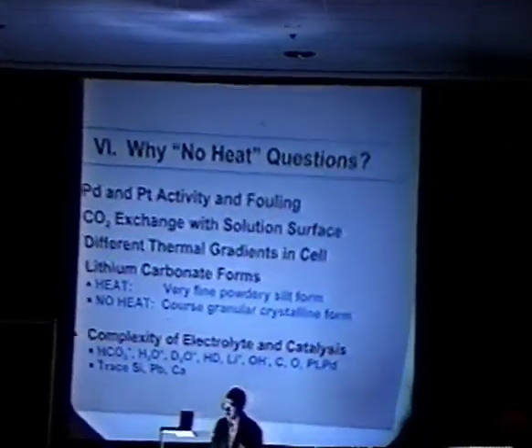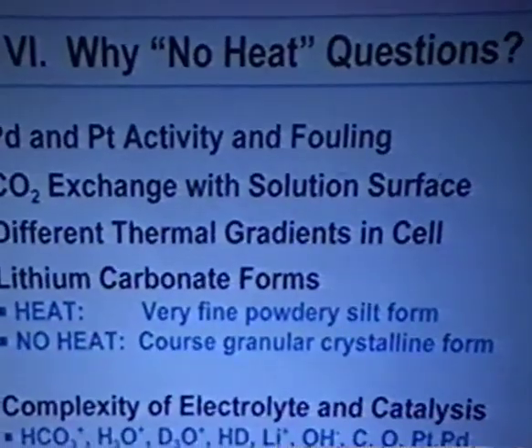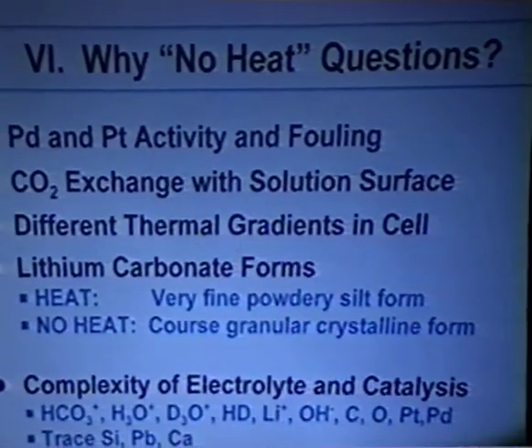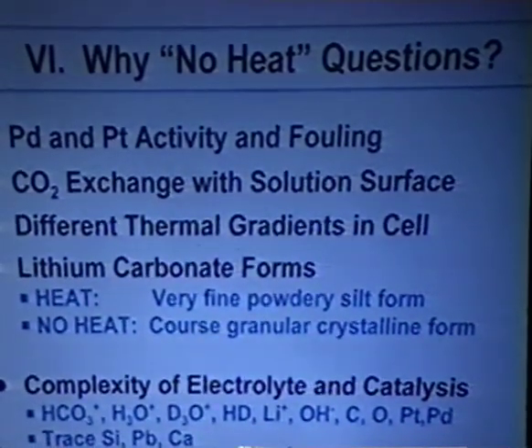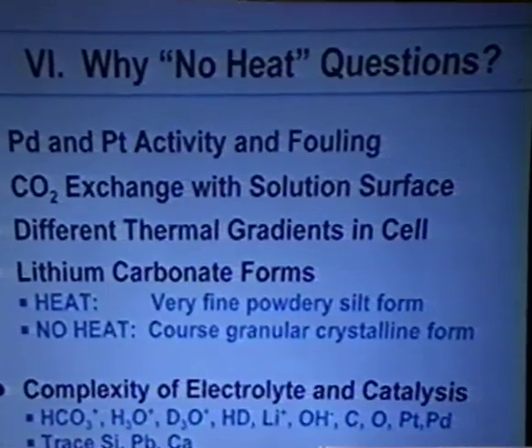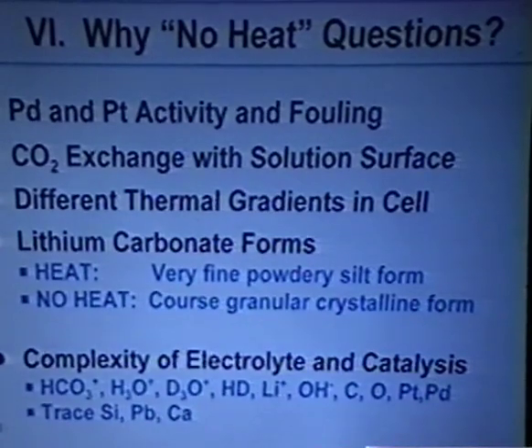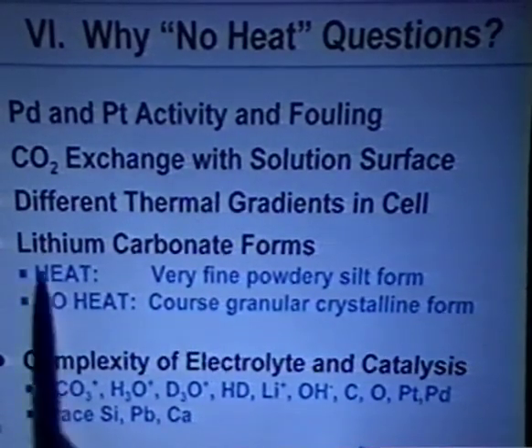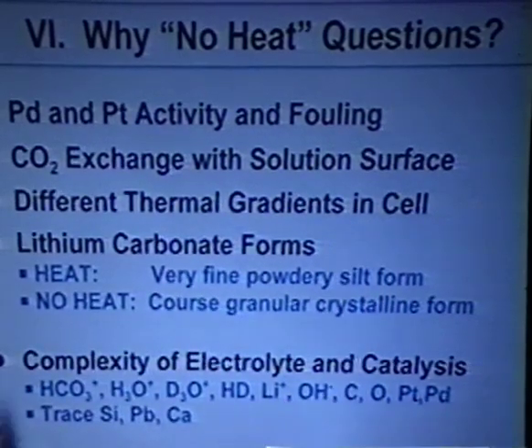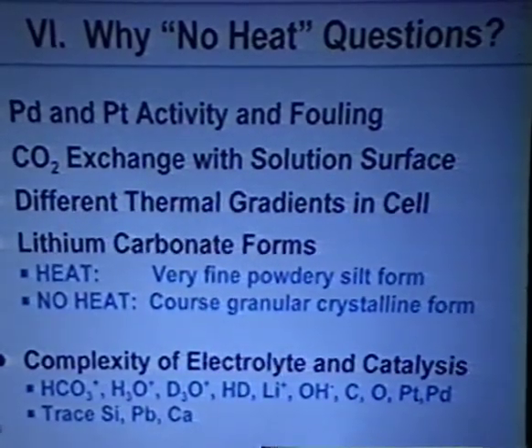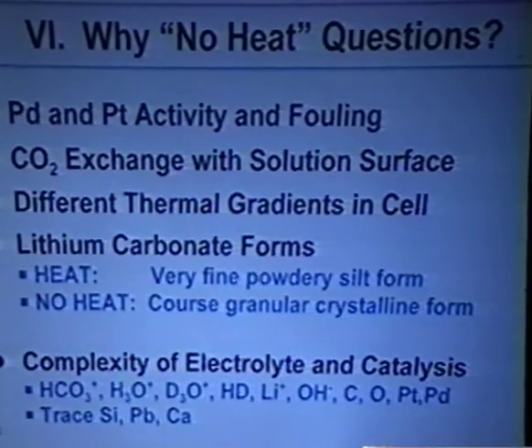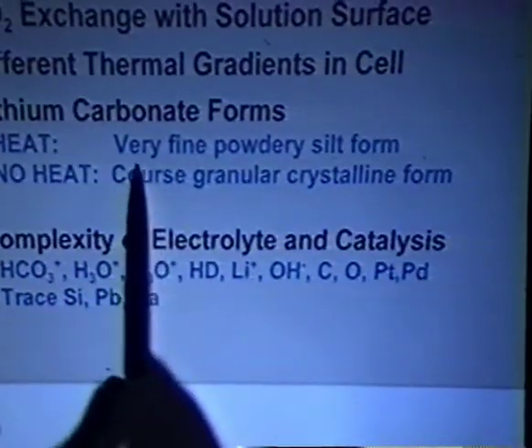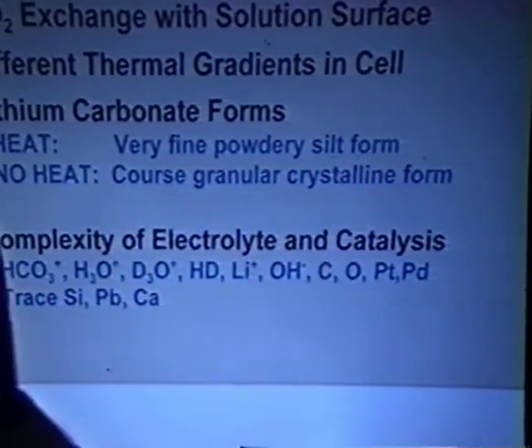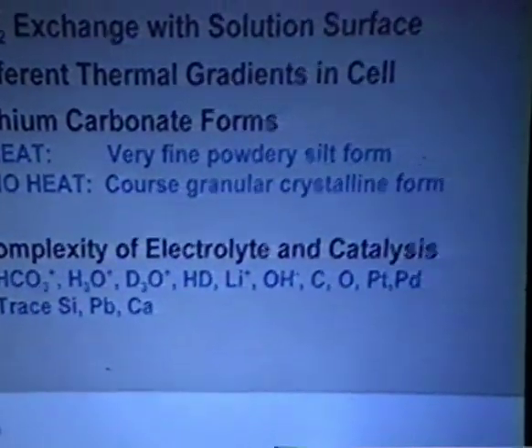Why no heat? Basically, I think a lot of it's related to palladium and platinum activity and the issue of fouling. We have seen silicon in several of the post runs. Silicon comes obviously from the beaker that's in there. CO2 exchanges with the solution surface can be different days depending on partial pressures. Also different thermal gradients in the cell. There have been several what I call anomalous differences between the top temperature and the bottom temperature in the cell. Lithium carbonate forms, again in the heat runs, is a very fine powdery silt form, and in the no heat, a coarse granular form.